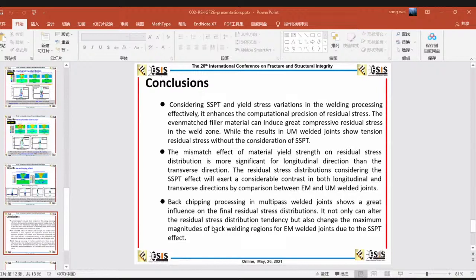This is my conclusion about the investigation. The first one: considering the SSPT effect and the yield stress variation in the welding processing effectively enhanced the computational precision of the residual stress. The second is that the mismatch effect of material yield strength on the residual stress distribution is more significant for the longitudinal direction residual stress than the transverse direction. The residual distributions considering the SSPT effect show a considerable contrast in both directions by comparison between the even matched and the undermatched welded joint.